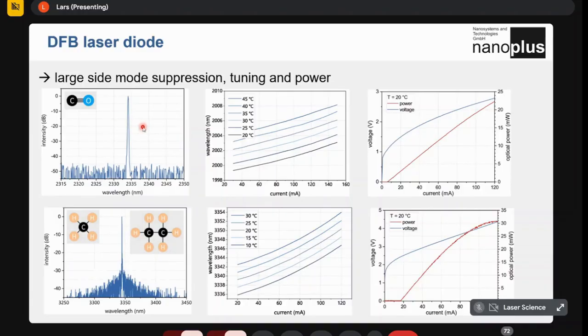This is the little red line that we've seen on the other slide, which I asked you to remember. And here you don't have any CO, so you don't see any absorption lines. The same counts for methane, ethane, here at 3,345 nanometers, tunability and the PI curve, the power curve. Also in this case, you don't see any absorption lines because they are not present while we did this PI curve.